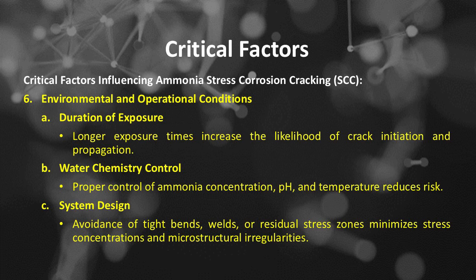Critical factors. Number 6 is environmental and operational conditions, includes, number A, duration of exposure. Longer exposure times increase the likelihood of crack initiation and propagation. Number B, water chemistry control. Proper control of ammonia concentration, pH, and temperature reduces risk. Number C, system design. Avoidance of tight bends, welds, or residual stress zones minimizes stress concentrations and microstructural irregularities.